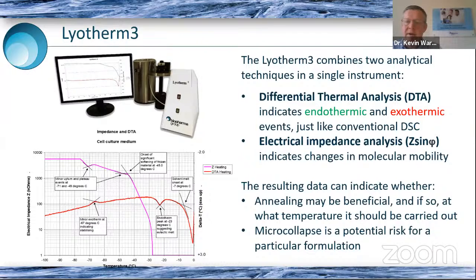And what would happen is that when we froze the solution to very low temperatures, we saw complete resistance, in other words, no electrons flowing at all. And we would then slowly warm it. And usually before we expected there to be any mobility, we would start to see the resistance reducing.